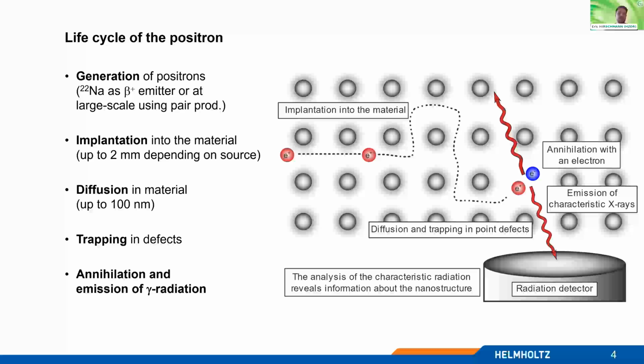You can implant the positron in the material, but if you vary a little, you can also investigate thin films of 10 to 1000 nanometer, but I will show you this later. After the implantation, there comes a short track of diffusion in the material, so up to 100 nanometer, and at the end it gets trapped in some kind of defect till it annihilates with an electron and emits the gamma ray. And the gamma ray is the information transmitter. So when or how this gamma hits our detector releases the information about the material itself.